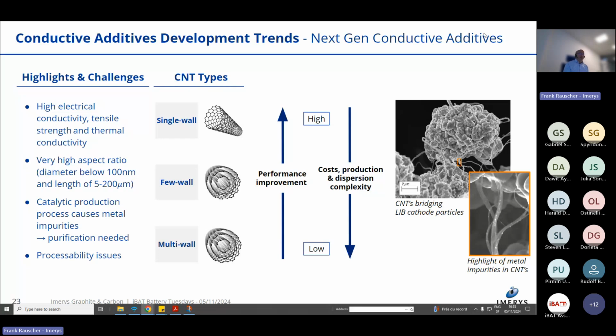At an earlier stage in my career, I was working for Bayer Material Science in Germany. And back in 2005, 2006, Bayer was leading when it came to carbon nanotubes. They developed those materials as conductive additives for their polymers, polycarbonate, polyurethane. And in 2009, they had the biggest production plant, a 200 metric ton per year facility for CNTs, but this all went away. So today you don't find a big CNT maker outside of Asia anymore, and the biggest ones are in China.